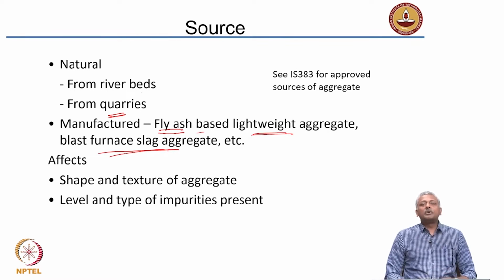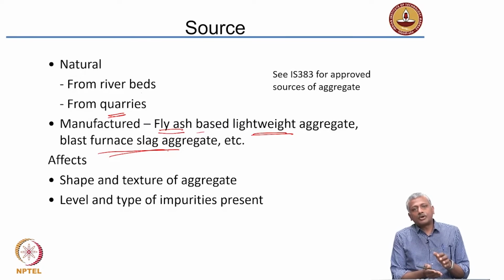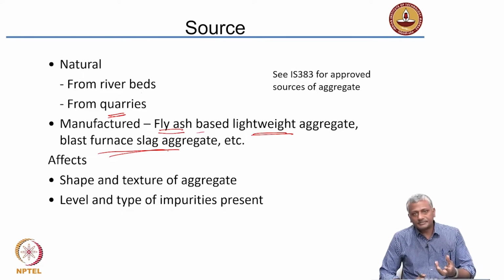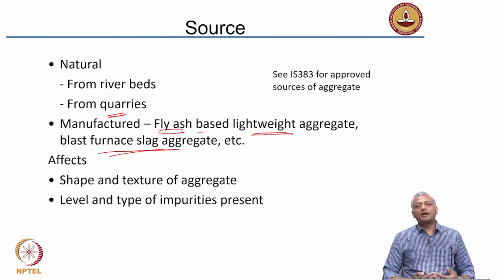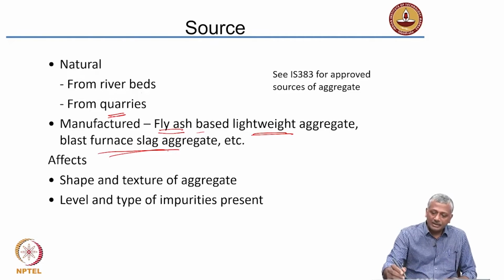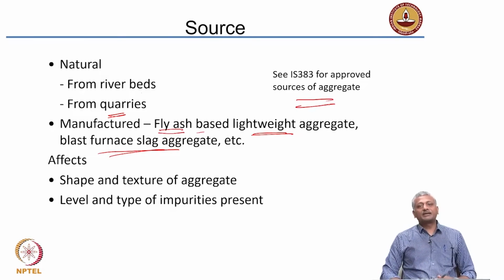The level and type of impurities that are present are also governed by where you are getting this aggregate from. Okay. Very often when you have a quarry, in between the deposits of rock, you may have deposits of organic material, right. You may have deposits of clay. So, a lot of the impurity that may come in along with the rock could be based on clay and organic material. Indeed, if you look at IS 383 for different sources of aggregate, it will tell you what to check for in terms of the materials that are not allowed to be used for aggregate and concrete.